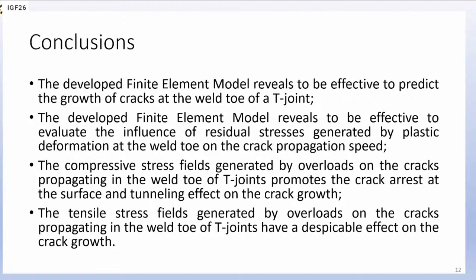As conclusions, we have the following. The developed finite element model proves to be effective to predict the growth of cracks at the weld toe of a T-joint. The developed finite element model proves to be effective to evaluate the influence of residual stresses generated by plastic deformation at the weld toe on the crack propagation speed. The compressive stress fields generated by overloads on the cracks propagating in the weld toe of T-joints promote the crack arrest at the surface and tunneling effect on the crack growth. The tensile stress field generated by overloads on the cracks propagating in the weld toe of T-joints has a negligible effect on the crack growth.